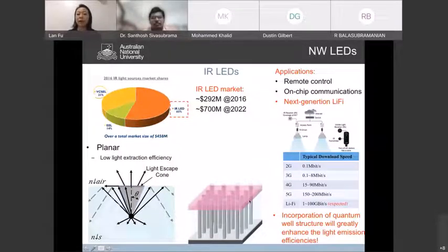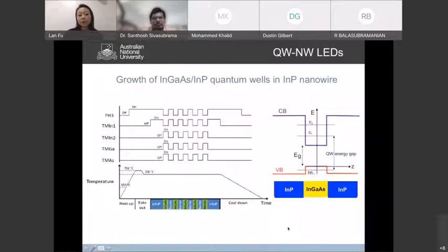Next, what we'd like to do is incorporate a quantum well structure into those nanowires and make them into LEDs. So how do we do that? The process is pretty easy. During our nanowire growth, we start with a standard indium phosphide nanowire growth, and then we switch gases. We switch off our phosphorus gas line and switch to the arsenic and gallium gas lines, so that we can grow indium gallium arsenide. By controlling the growth time, we grow indium gallium arsenide sandwiched between indium phosphide. Thereby, we create this quantum well structure.